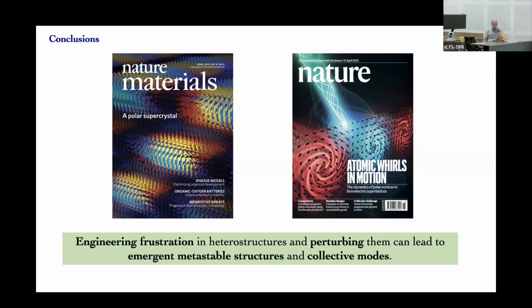Right. So there is a substrate in there too. The film is grown on a particular substrate. So there is a strain mismatch there, right? And so the substrate strain is such that in the beginning, as you grow it, the two mishmash phases are on either side of the substrate. So the average strain is 0, but individual strains are not 0. They are inhomogeneous strain. But what the system does when you do all this stuff is it finds the supercrystal whose strain is exactly matched to that of the substrate. So it becomes homogeneous 0 strain. It sort of gets lattice matched.